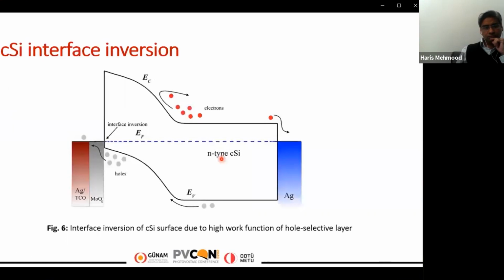Now we come to the results and discussion. As a result of implementing the high work function material with the crystalline silicon, it induces band bending. A significant amount of band bending happens at the crystalline silicon and molybdenum oxide interface. Molybdenum oxide is also a transition metal oxide layer. It is also a hole selective layer with a high work function of around 6.9 electron volt, which is similar to the work function of tungsten oxide.